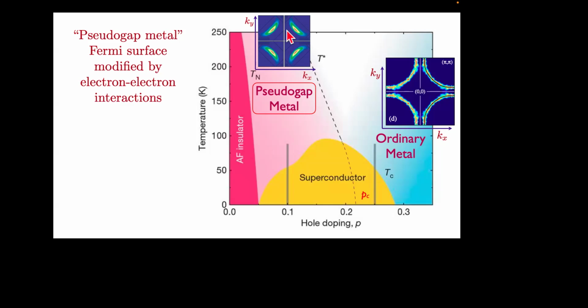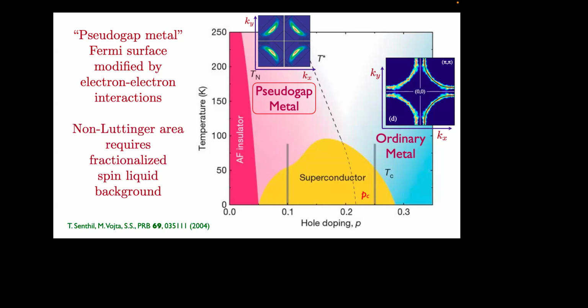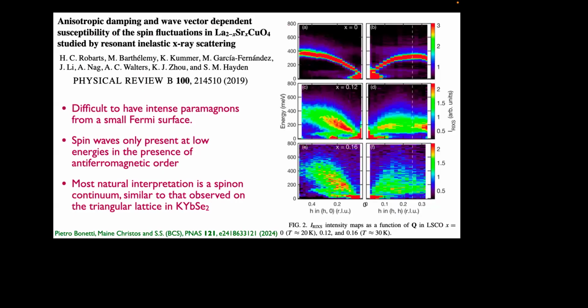But one thing one can say from theory quite confidently is whatever is the resolution of the violation of Luttinger theorem. In other words, can you come up with a theory which gives you a metallic state which does not obey the Luttinger volume? And in fact, you can. The way you get such things is by imagining that the missing electrons, if you think of these as small pockets, a lot of the electrons that were here have disappeared. So where are the missing electrons? Those missing electrons have to be in a spin liquid background. There's essentially a theorem that you can show that works. Of course, it's much harder to compute things in great detail, but that's what we think is happening in the pseudogap metal. And one evidence for these missing electrons is that there should be spinons.